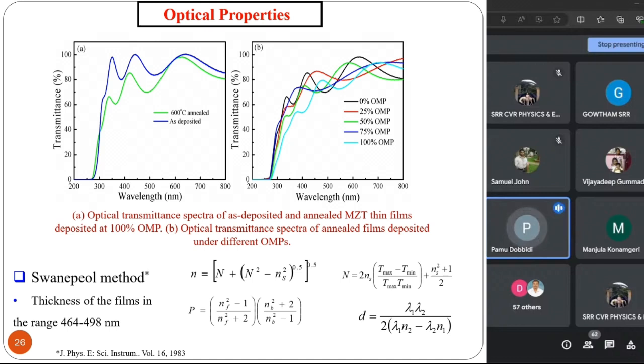You see that when you deposit these thin films, it's beautiful that almost 99% of the light will transmit through. What is the advantage nowadays? You look at buildings, Microsoft or Google, when they make the buildings, they make them with glass. Why do they make them with glass? Because if you deposit this material on the glass, the beauty is that it will absorb UV radiation. Now in summer it is very hot here, there will be UV rays coming, and they are harmful to our body. So if you can coat this material onto the glass, there is no light you are losing, because 99% of the light is transmitting through the magnesium titanate material, and it will absorb the UV radiation, and it will reduce the heat inside the room also. That is the beauty of this coating.